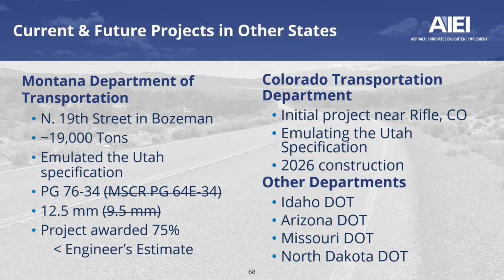No, I think that a little bit of confusion is arising from the fact that we started in Montana with a MSCR grade. We are a MSCR state. Our future projects, I believe, are all going to be MSCR grades. There were some issues getting the mix design to pass under the original spec that the Montana DOT had with the contractor. Therefore, with about 2 weeks prior to paving, there was a switch to the Utah spec, which included a PG 76-34, an M320 binder. And so the shift was made to a straight PG grade versus a MSCR grade. And I think that may be where the confusion is arising.